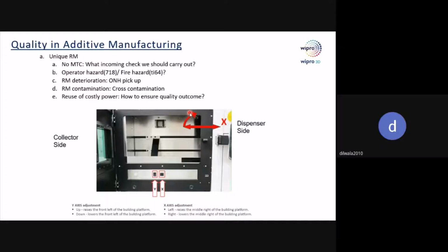Then you have raw material contamination. See, for example, you get a billet or a slab. It is no way possible that you can mix up two incoming raw materials and have a cross contamination. That's not possible, right? But when it comes to very fine powder particles less than 63 microns, and you're using, say, a common machine, and you're not cleaning the machine and accessories properly, then you have every chance you will be mixing up and contaminating one powder with another.